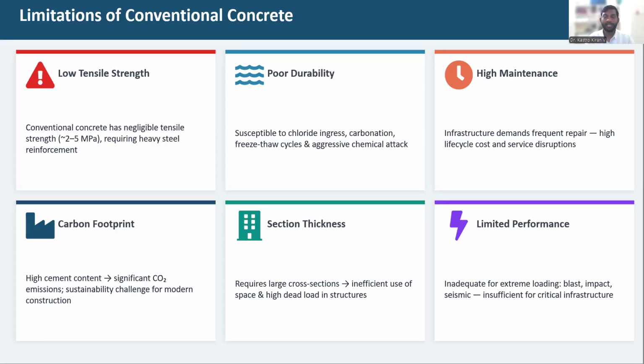But we have some limitations with conventional concrete. Typically, conventional concrete lacks tensile strength, giving very little, approximately 2 to 5 megapascals. That's the maximum we can attain. It also has poor durability because of the larger amount of pores compared to other types of concrete. So it is susceptible to durability problems. For example, when I expose conventional concrete to acids or sulfates, there is a high chance of deterioration within the first 14 to 28 days or within the first 56 days itself. That's again one of the problems, and the durability problems lead to higher maintenance costs. So that is also one of the disadvantages.